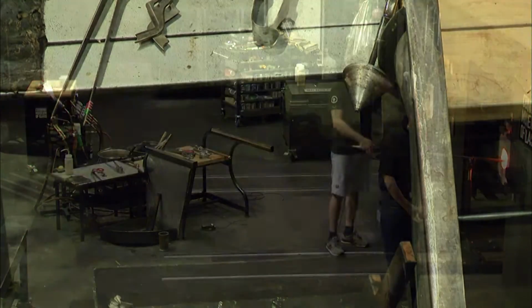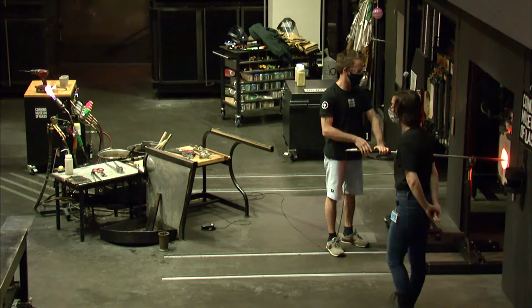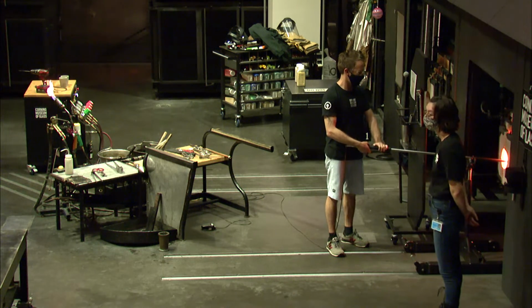There's actually a bed of something like sand, it's called grout, in the bottom of these furnaces. So if we happen to drop a piece of glass inside of that furnace, once it cools down at the end of the day, we make sure we get all of that glass out of the furnace because it will start to chew away and eat at the brickwork inside of that furnace as well. So, nice stuff. Not anything as fun and dramatic as the acid dripping through the decks of the alien ship, but over time it does create a little bit of damage.